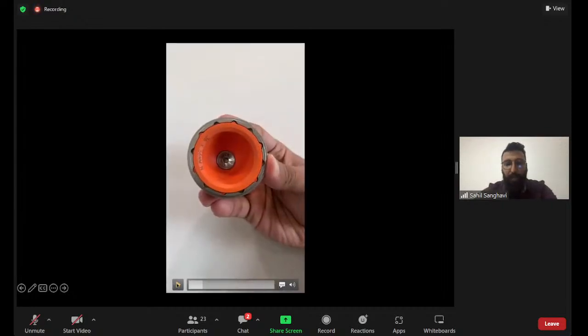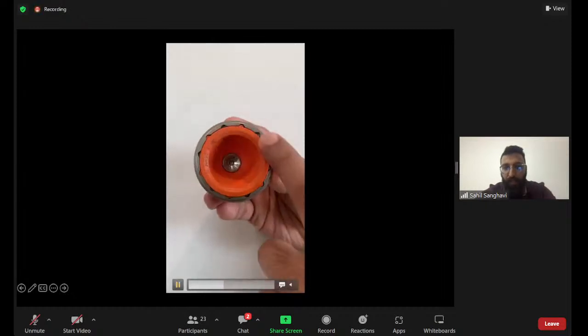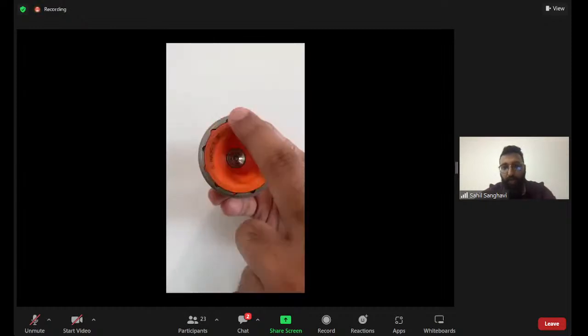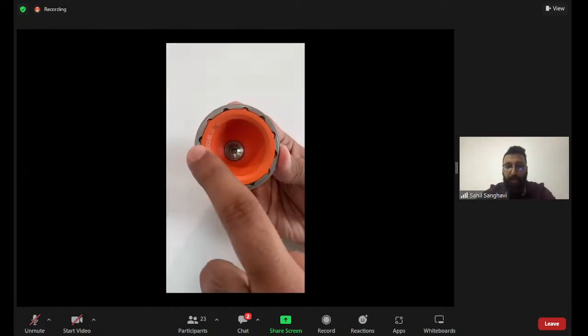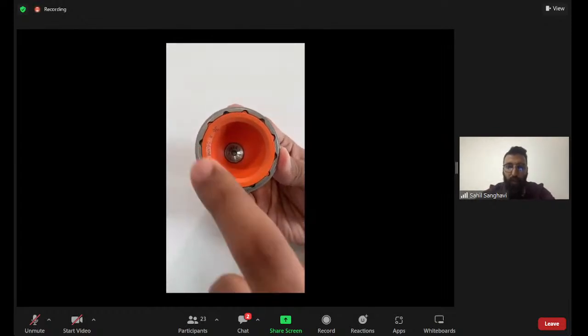So another practical tip here is that once you've put in the ceramic liner, move your finger around the edge of the liner and the shell. Make sure there is no step-off or malseating. Both these surfaces should be absolutely flush with one another.